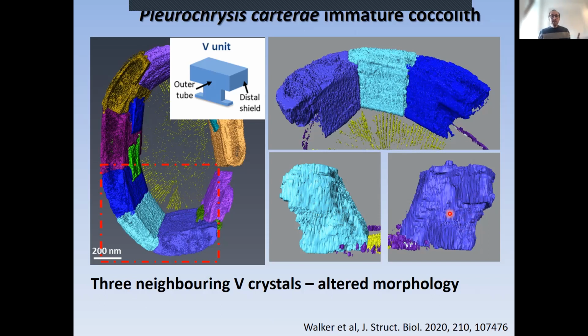So what this is basically telling us is that one of the mechanisms for controlling morphology is a matter of competition for space. So we have crystals that are growing in a crowded environment. They have different crystallographic orientations, so they're going to be growing faster along different directions. And by doing that, they pin the growth of the crystals that are just adjacent to them. So they're restricting the growth of that crystal, and that is helping to give rise to this kind of morphology that you observe. So it's a matter of competition for space, which again means that the process doesn't have to be very complicated to template the morphology.